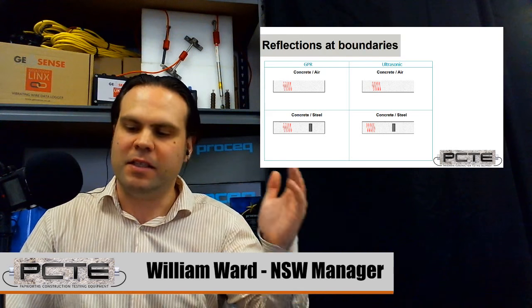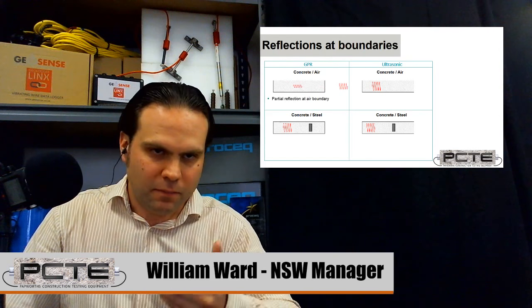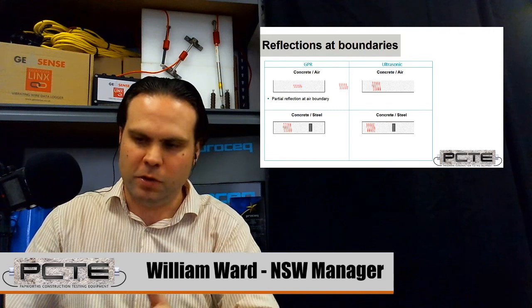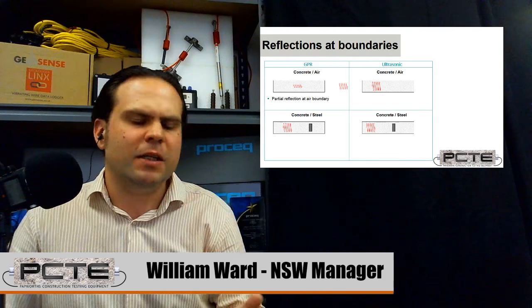Now, to talk about why this is, we need to look at what happens when a signal is sent from the surface of the concrete through the material. If we send a sound signal or a radar signal, so we'll start by sending a radar signal. Where it meets a concrete air interface, it reflects a portion of that energy. A lot of the radar energy keeps going past the back of the structure into the substrate, and what that means is we can see that join weakly, but we have the ability to see beyond that point in the structure as well. The things that you see strongest with an imaging technique are also often causing a shadow or a block of what's behind them.